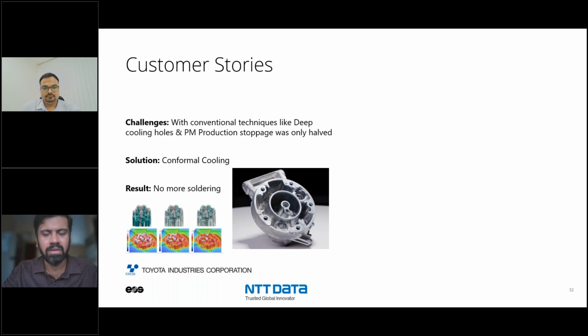Some other customer stories on die casting. Toyota, along with NTT Data, were manufacturing these compressor housings, right? And it goes to 10 million shots or so. They encountered one of the defects of die casting, which is soldering. Basically, aluminum gets stuck onto the tool. They tried deep drills and things like that, and even with that, they were able to reduce such defects to a great extent, basically to half. But it still had to be optimized. So with conformal cooling, now the soldering defect is zero, right? So when it comes to manufacturing, the tool does not have any soldering defects at all.